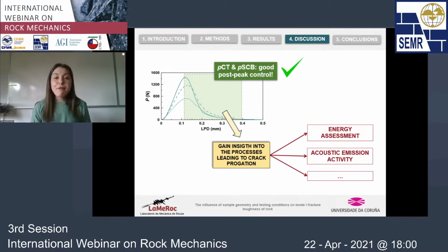And the fact of controlling the post-peak can be really useful, because we have here a lot of information that we can use to gain insight into the processes that lead to the propagation of the cracks. So in this study, we have used this information to perform an assessment of the energy, and also to analyze the acoustic emission activity on the post-peak. But this can have many other applications.